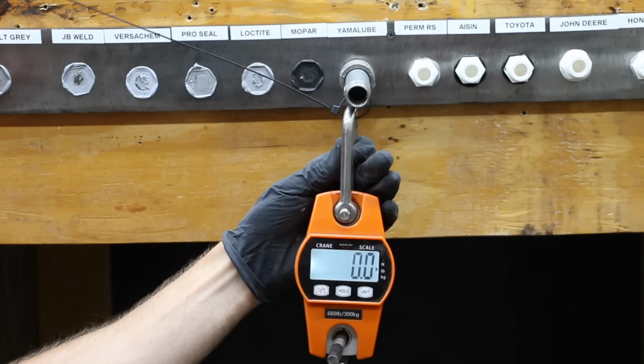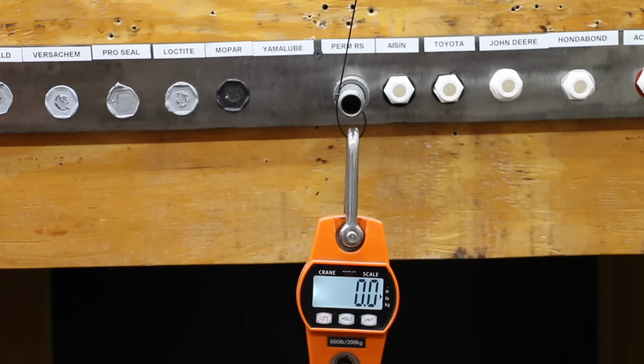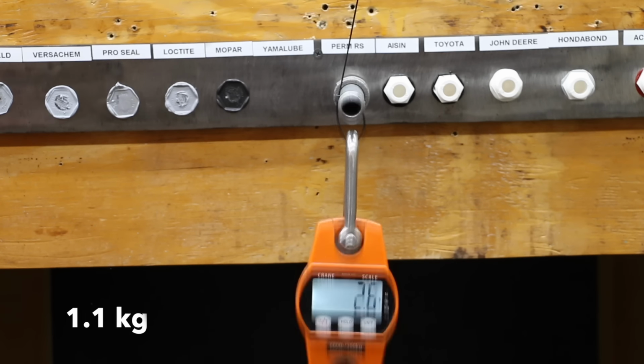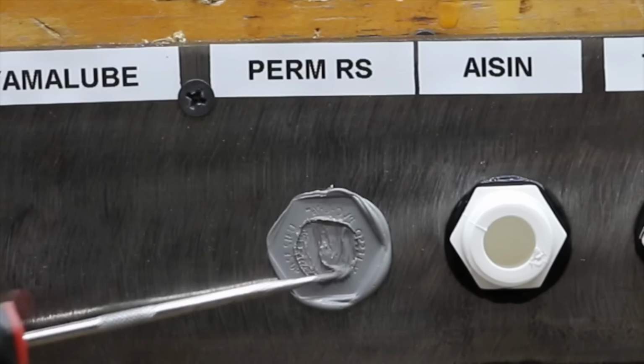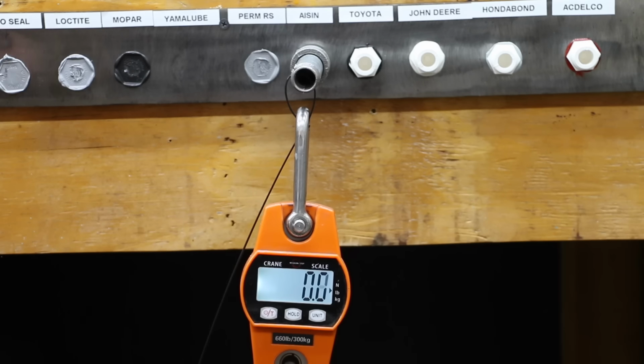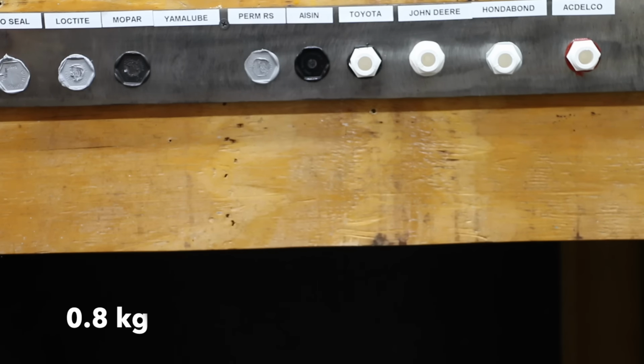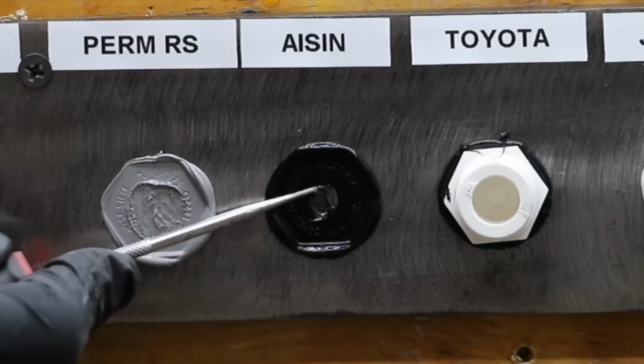And the Yamalube let go very quickly at less than a pound. And the Permatex Right Stuff performed very close to the same as the Permatex Ultra Grey, quickly letting go at 2.4 pounds. And the AISIN was very quick to let go at 1.8 pounds. The AISIN is almost fully cured across the entire test area.